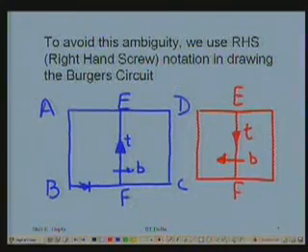What is the consistency here? Angle between B and T, that is B to T, is 90 degrees. Define the angle like this. From B to T, the angle you define is 90 degrees. And if you look at the vector, if I talk in Cartesian geometry, let us say this is a simple cubic system where I can talk of the Cartesian geometry, look at the vector B cross T.